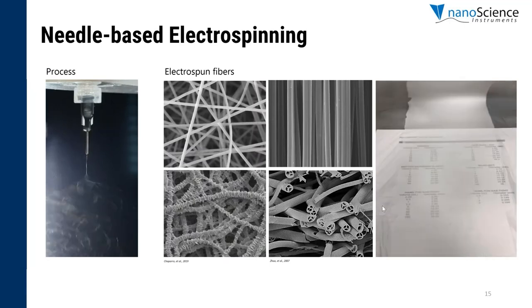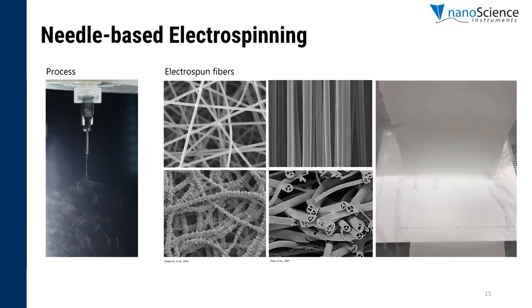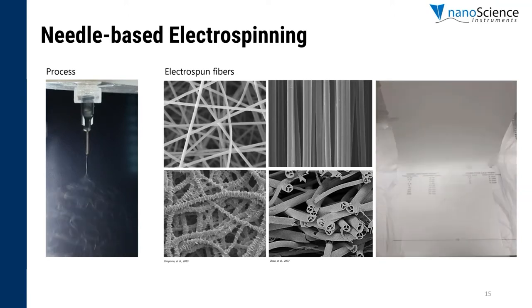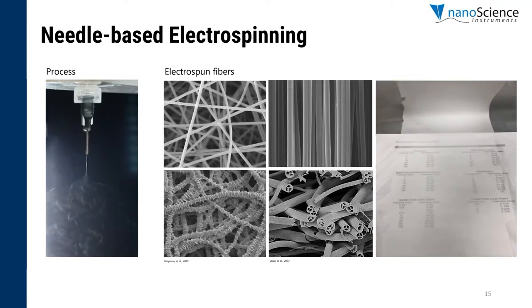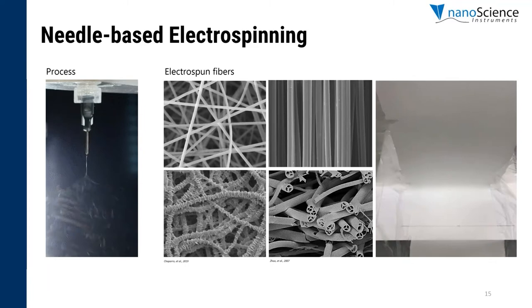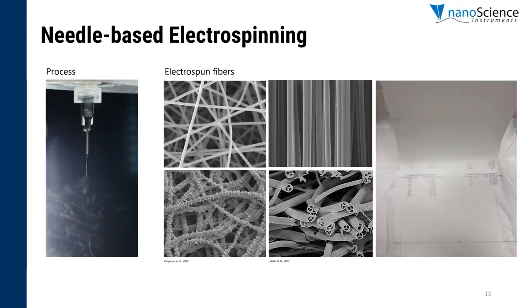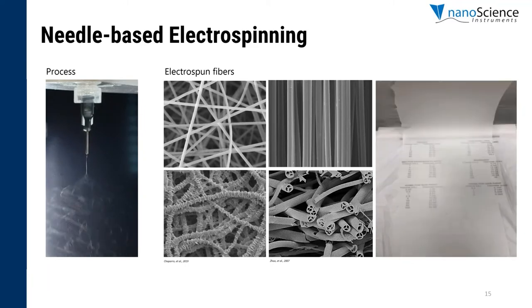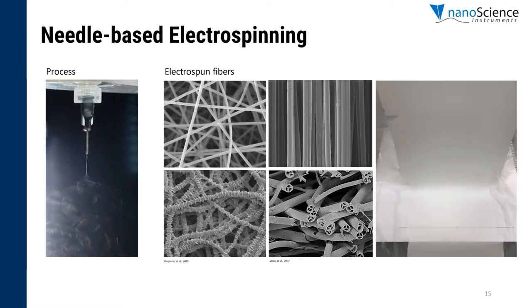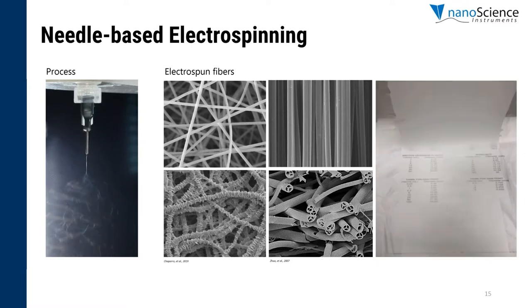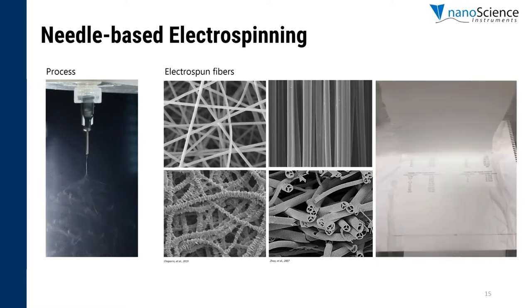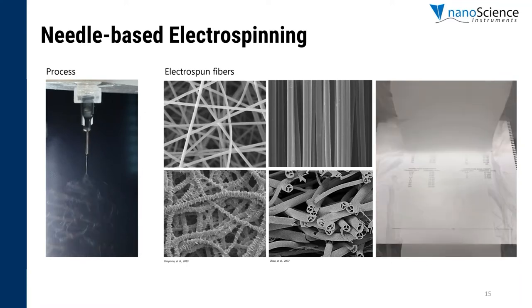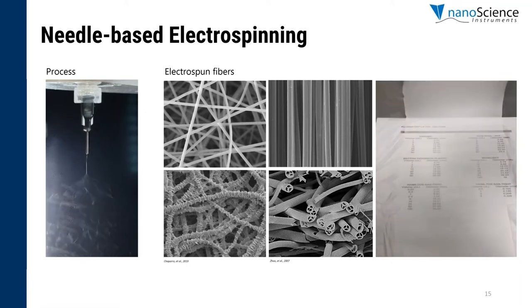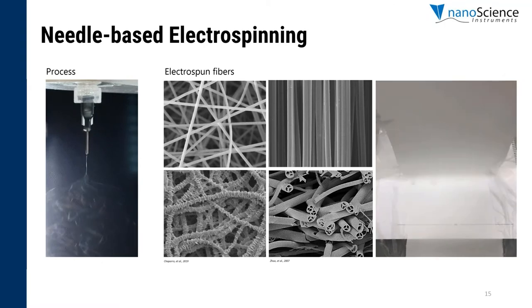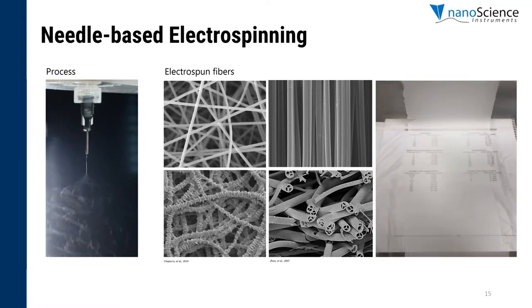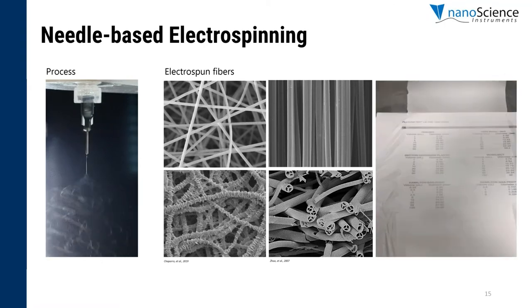Here we have an illustration of what an optimized electrospinning process looks like. This is the picture on the left. Due to the applied voltage and charge accumulation, you can see how the solution is ejected from the needle tip. In the lower half of this same image, you can see the electrospun fibers, and this is where the solvent is slowly being removed due to the bending and the whipping motion, which allows the solid fiber to be formed. A few examples of electrospun fibers that can be developed are shown in the middle section.